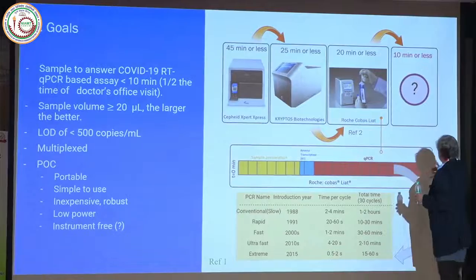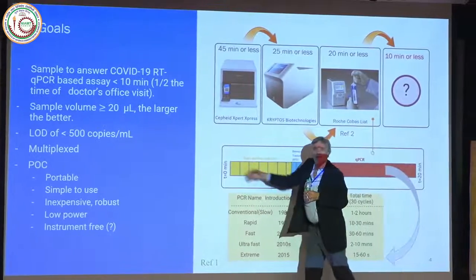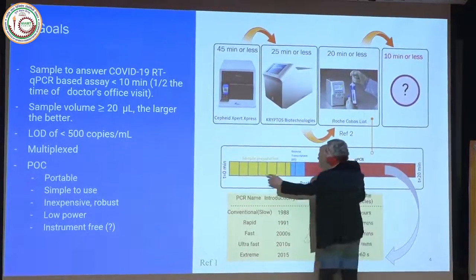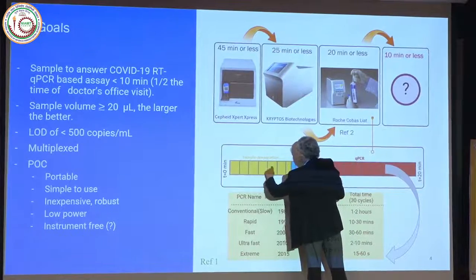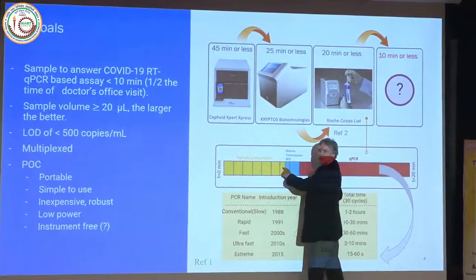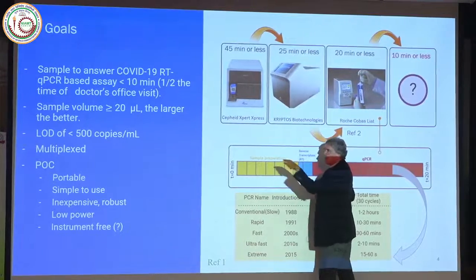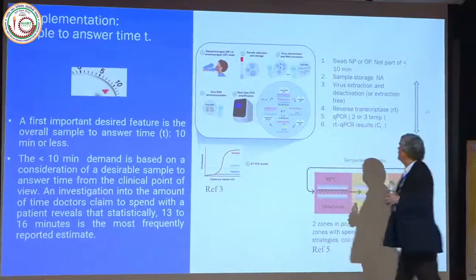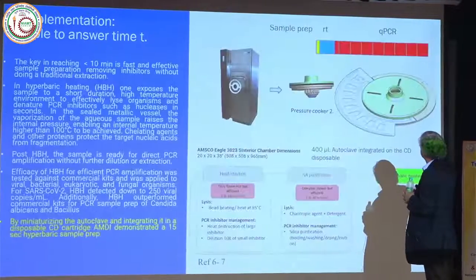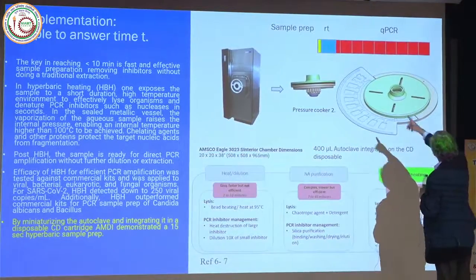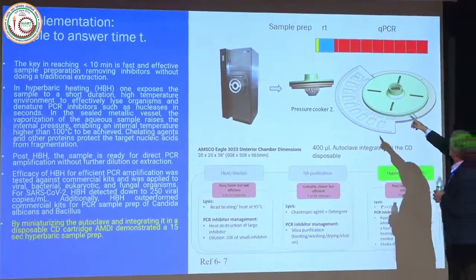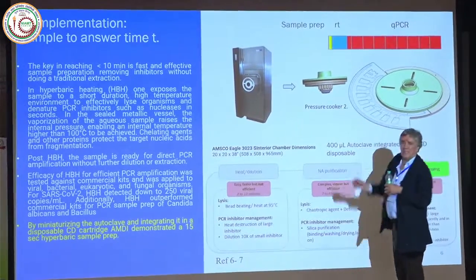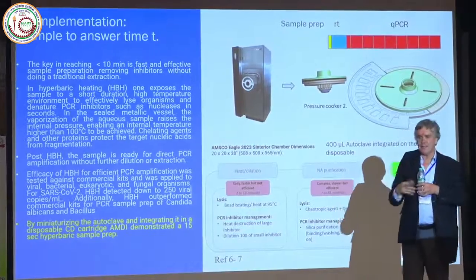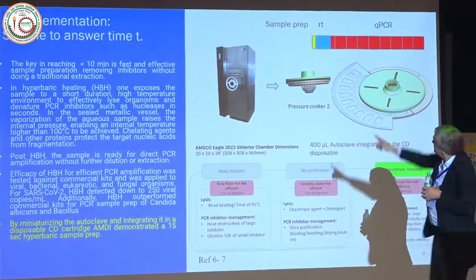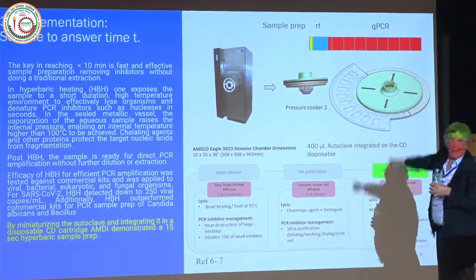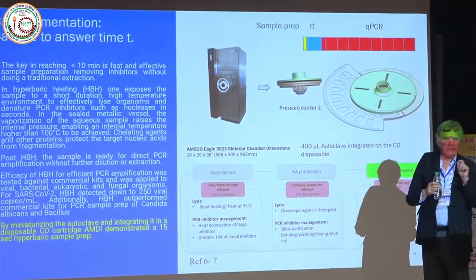This one. You remember this bar, right? So what I have done is I found a technique to bring 6.5 minutes down to 15 seconds. So we see, for short, that first segment is the RT, the reverse transcriptase. I haven't changed that, that's still 1.5 minutes. But you can see that the yellow area there has now become 15 seconds.